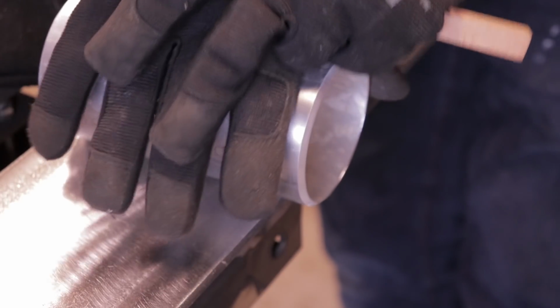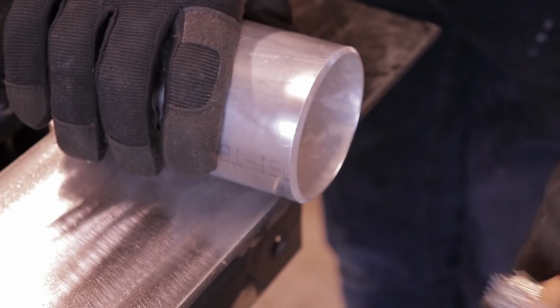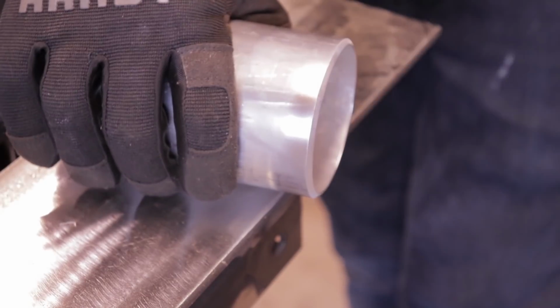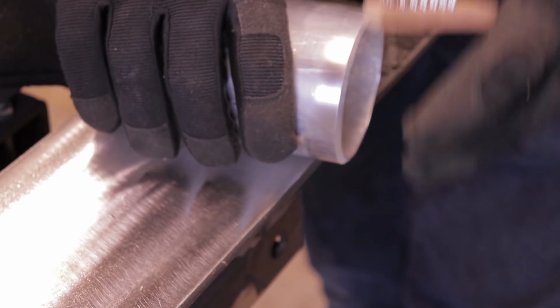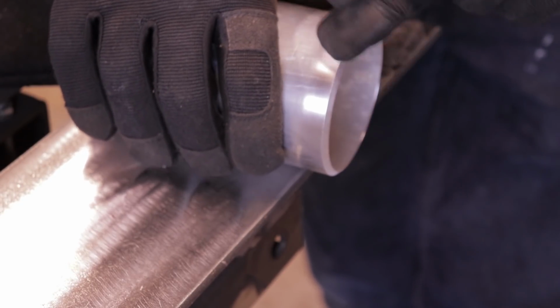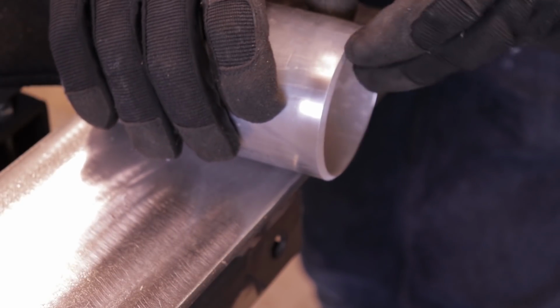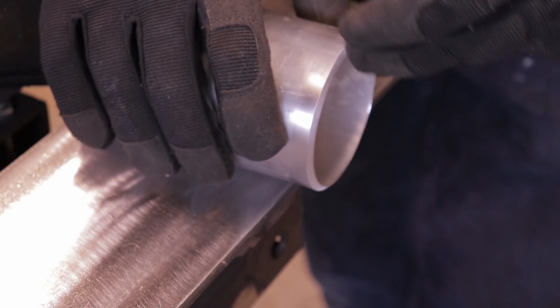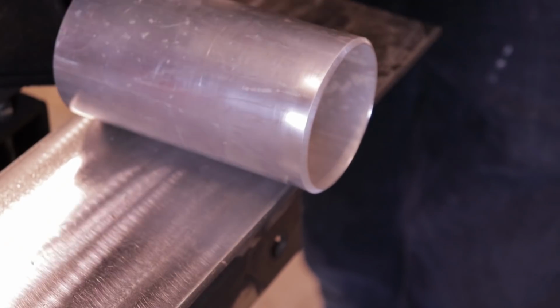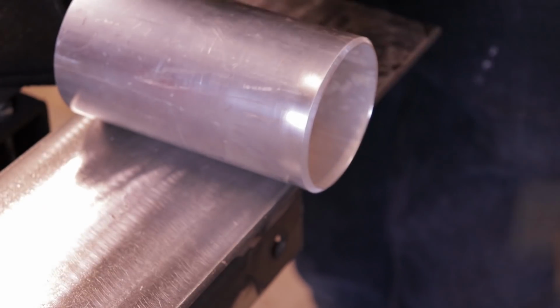So those are actually encased in the aluminum. You'll see it in old aluminum especially that's been outside, and that's actually why it's shiny underneath, because the cloud that forms with the oxide layer that's sucking in all the specks and stuff traps that. So when you're doing this with the wire brush, it's cutting that out, basically removing all the debris. And if you don't do this, then when you weld, your cleaning action does a good job of cleaning the oxide layer, burning that off to get to the actual aluminum, but it doesn't clean dirt. So it's basically like welding on a dirty piece of metal, because it's just going to suck all that dirt or oil that was on there before in.